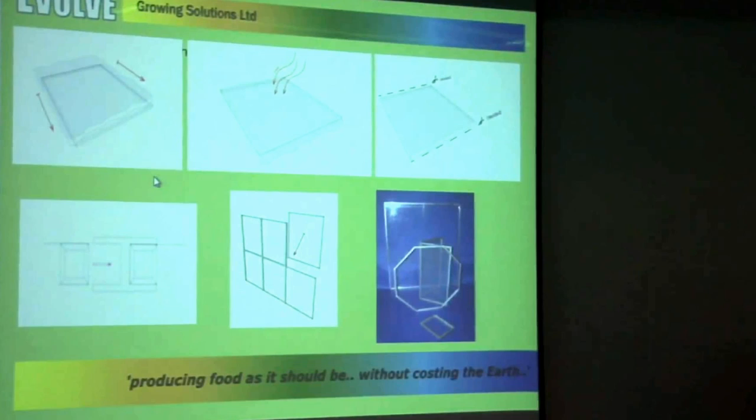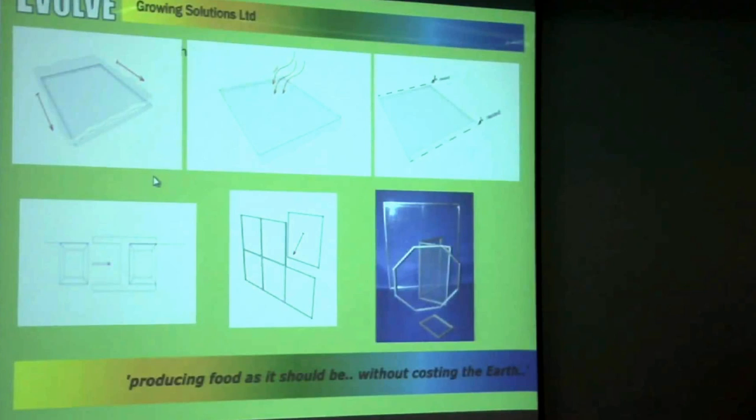Okay, I went to them with an idea, having known the properties of heat shrink with ETFE, and said, could we create glazing panels for this? This is not marketed directly for glasshouse so much as the architectural applications. But it still has a very good place for small-scale ETFE structures that can be put up very easily. We take the film, we process it, we secondarily process it to a wider size, we put it inside the metal panel, as you've seen outside, and then you heat shrink it on, and that heat shrink has an incredible tensile property that we're testing right now.